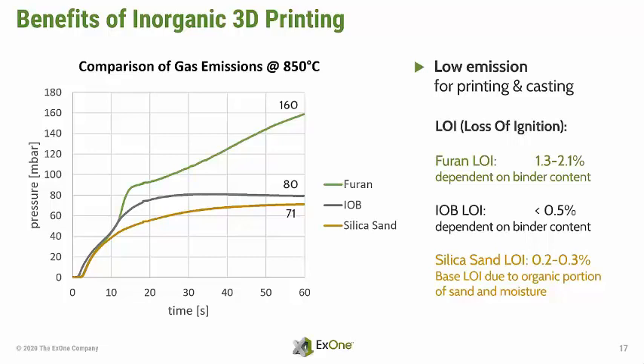The shown graph compares the loss on ignition of a 3D print with Furan and inorganic binders. The LOI percentage is kind of a reference for how much binder was used and is referring to the surface underneath the curves in the graph. As you can see, the pure silica sand by itself is contributing about 0.2 to 0.3% of LOI. The inorganic binder is adding just very little to the final LOI, but at Furan, the combustion of the organic binder is creating significantly more gas emission.